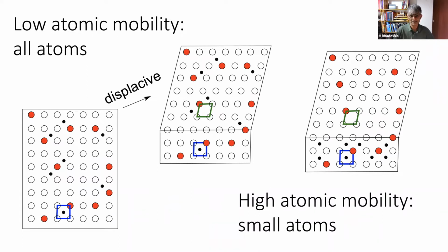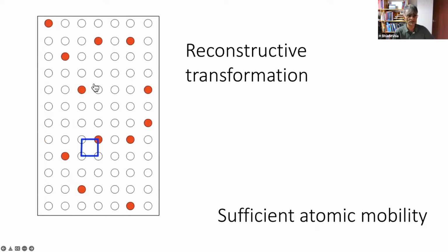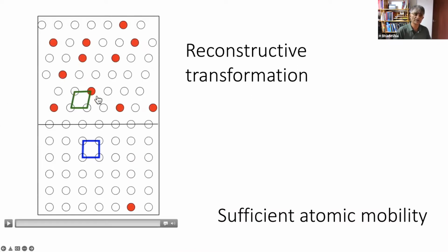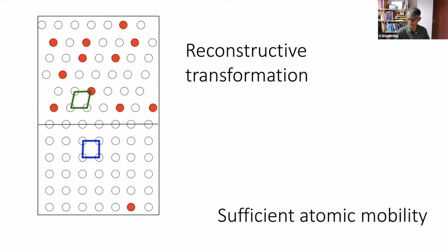And the second mechanism of transformation is what we call a reconstructive transformation. So we start off with the same lattice, but we break all the bonds and rearrange them into the new pattern. And that process requires diffusion. And therefore, you will also get composition changes involving all of the atoms. So I'm going to break up this lattice completely and rearrange the atoms into a different pattern. And in that process, the atoms reach their most comfortable positions. So you are much, much closer to equilibrium, and there is no macroscopic change in shape. So in other words, there will be a strain energy term due to volume change, but it will be relatively very small.